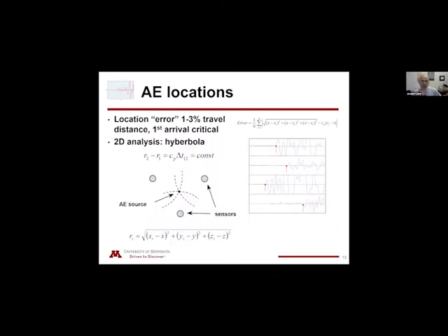Okay, a nice way to look at locations is graphically, and for a 2-dimensional problem, it's easy to show, easy to construct. I should mention something about error, and of course this is in quotes because we don't know the answer. So we calculate a location. From that calculated location, in reference to the position of each sensor, we can calculate a distance. And we can compare that distance that we compute with a distance that we also compute, because we have to find the original time, the time in which that event took place in reference to the arrival of the signal. So this time difference multiplied by the P wave velocity gives us another distance. And this difference for each sensor gives us a measure of, we call it error.